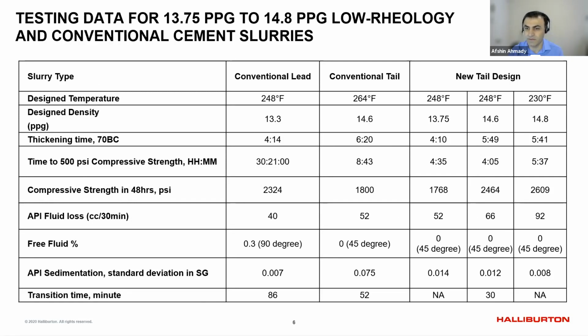Then in the next step, we could see room there. Okay, we could change the density back to the original one, 14.6. In some cases, when they had higher formation pressure and more requirement for maintaining backside pressure, especially at the end of the job, we could see room to increase the density and improve the design. And with all those changes, the viscosity of the new design versus the old design is less than half, looking at this one.